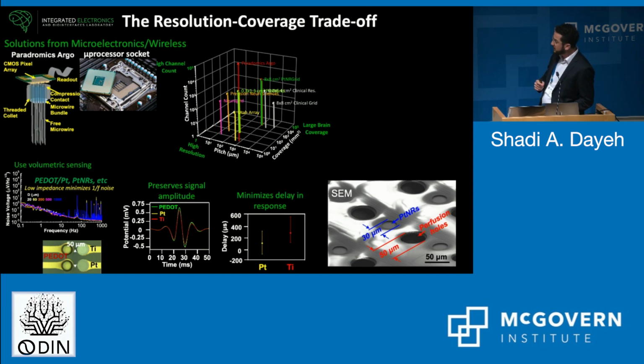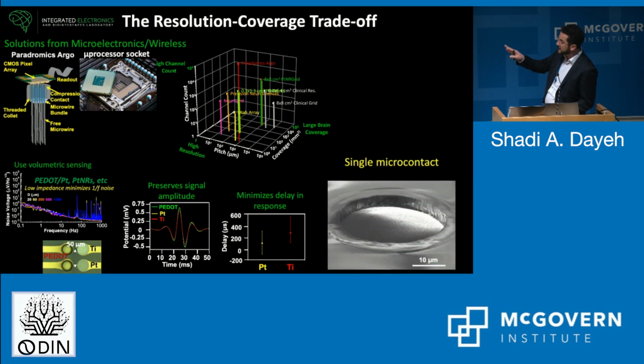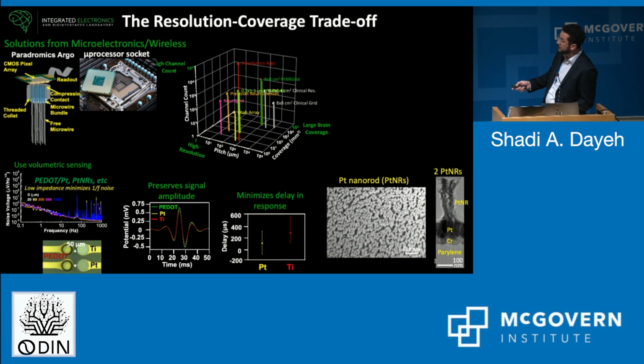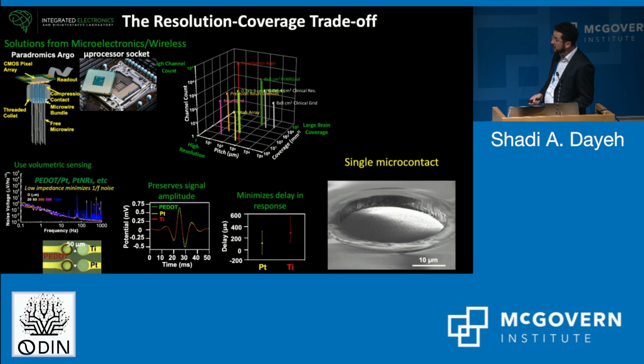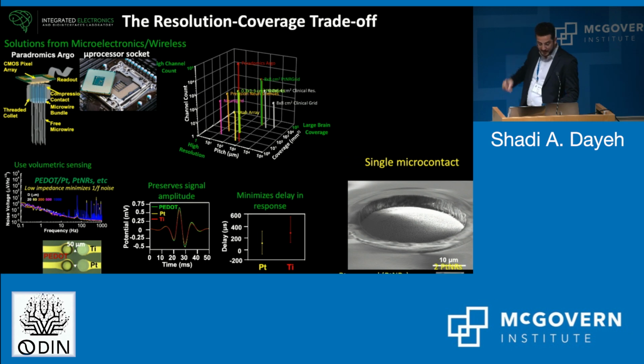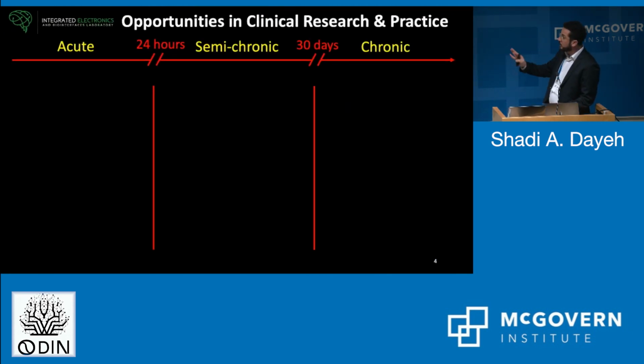The devices that we will talk about today are platinum nanorod grids. This is a scanning electron microscope image of how such a grid looks. It has perfusion holes. The overall thickness is about 6 microns, and the contact diameter is 30 micrometers. Recessed below the surface is a mesh of nanorods that are about 50 nanometers in diameter and 500 nanometers in length. This is so that if the electrode moves on the surface of the brain, the rods wouldn't rub against the tissue. We classify the use of these electrodes from a clinical perspective, similar to the FDA classifications.